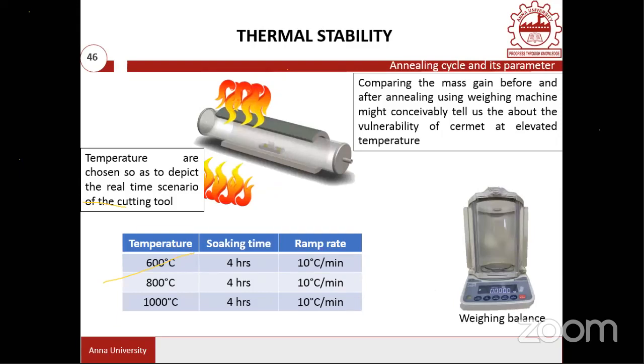So it will be subjected to 600 degrees centigrade for 4 hours. Once that 4 hours is over, then the furnace will be allowed to cool on its own rate of cooling. Okay. So like that, now we have taken different temperatures and constant soaking time. And after annealing, we can see what is the variation in the hardness value, whether any mass gain or mass loss is there in the material, or any new phases are formed due to this temperature exposure, or probably we can also measure the grain size. What is the grain size before annealing, after annealing, if there is any grain growth possibility.